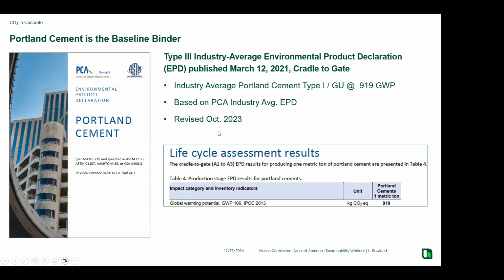When we put that all together and we look at the industry average environmental product declaration, or an EPD, we discover that the average CO2 associated with Portland cement's production is 919 GWPs, which means that for every metric ton of cement, which is 1,000 kilograms, we produce 919 kilograms of CO2. So it's a straight ratio. Once again, for every 100 pounds of cement that's manufactured, on average, we produce about 92 pounds of CO2.